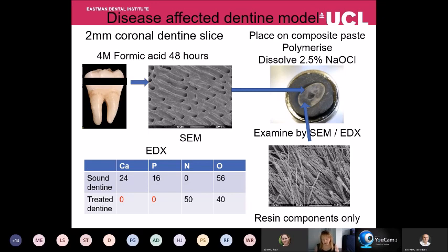We can then place the resultant flexible disc of collagen that we've got left on top of different composite pastes. We then polymerize the paste and dissolve away any of the remaining collagen with sodium hypochlorite. And what we get left with is, on here, this is the composite. We've got an imprint of the collagen, the dentine slice. And you can see dark areas here. And in these dark areas, what we find when we look under SEM are really long resin tags. From elemental analysis, that's EDAX, we can see that these tags are composed largely of the resin components. They're not the solid, they're not the polymer, it's the monomers that are forming these tags.